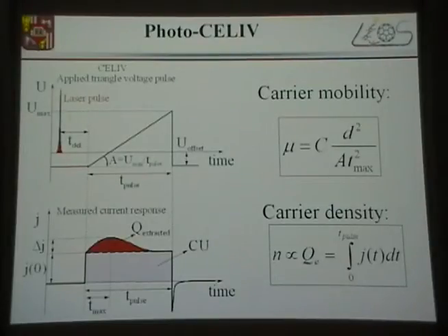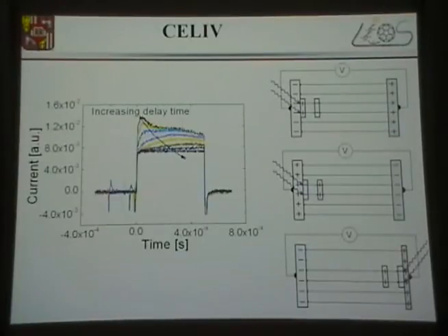So you say that this is a fixed, let's say, host impurity. But if you do photo-CELIV, you have electrons and holes in equal amount, and one is faster and the second one is slower. You extract, let's say, the first, and you say this is the mobility of, you don't know what, but you assume that. But the hole is still inside, and it is drifting to the contact and comes out later. Do you see the second mobility somewhere in your transit?